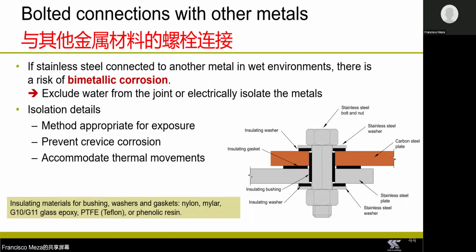So the main strategy to prevent bimetallic corrosion is to separate the two dissimilar metals. And this is something that can be achieved by using insulating washers and bushes. But because these insulating components are compressible, they can only be used in bearing type bolted connections. So the figure in this slide shows how you can achieve the separation between the carbon steel and the stainless steel plate using insulating components. And if you use this type of solution, you need to make sure that the bushing is able to resist the bearing pressure at the bolt. So in this case, it is recommended that you make sure that the threads of the bolt are not included in the shear plane in order to prevent puncturing the bushing.